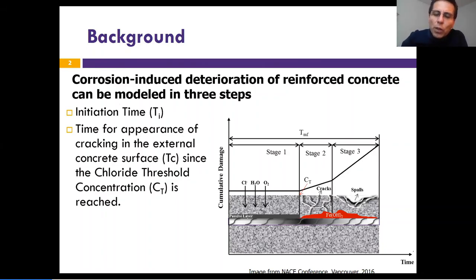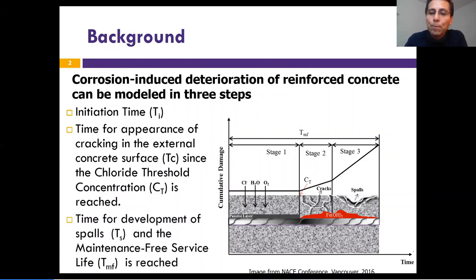And stage two, we call it the transition time, where there is an implication of these corrosion precursors in the rebar. And stage three, we call it the propagation. The propagation is where you see, in red color, the corrosion products. Once you activate in stage two, the activation will induce these corrosion products and will increase the volume of the original size, and then it's going to start to form the cracks. So these three stages are the damage evolution in terms of corrosion for the rebar in concrete.